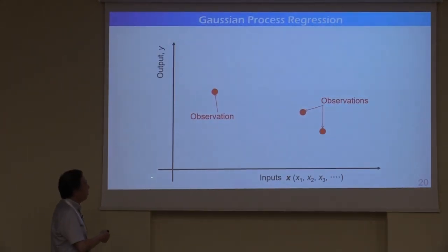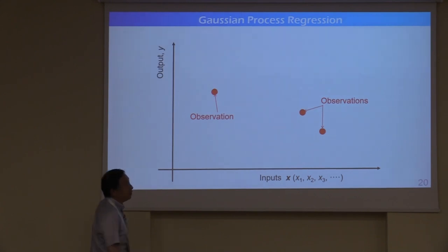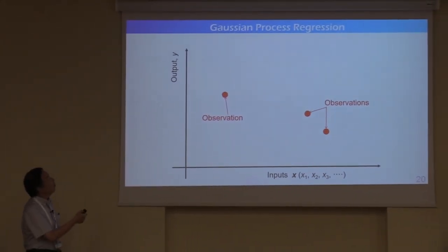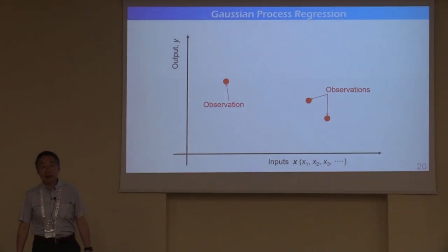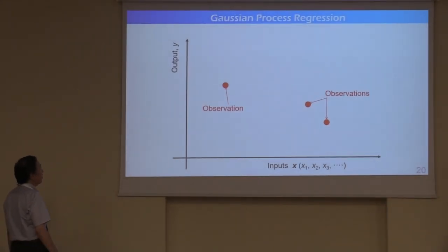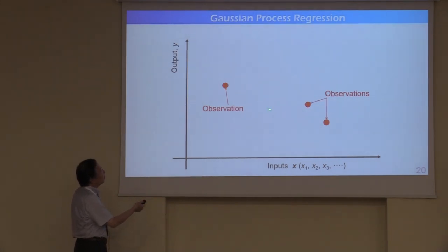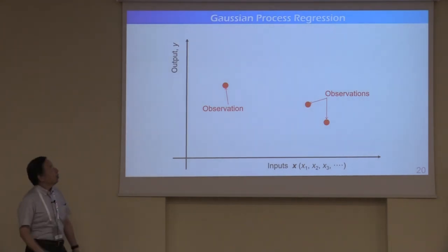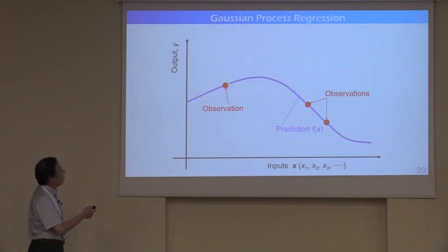And we put these 36 features in the horizontal axis. Although it looks like one dimension, it is actually 36 dimensions. And the vertical axis corresponds to the output. In this case, this is the lattice thermal conductivity. And as a model, we took the so-called Gaussian process regression. With Gaussian process regression, if there are some observed results, in this case computed results, here and there, then this regression can make this type of model.